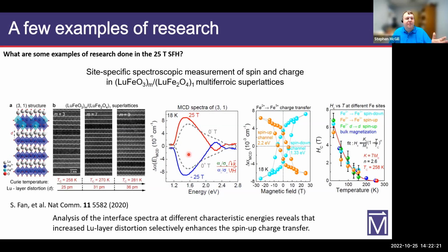So as we were talking about earlier, sometimes light is used to control or to tune the properties of the system. Well, here's an example of a ferroelectric ferromagnetic system. It's a superlattice of lutetium iron oxide. And it's a superlattice with different valencies of the iron oxide and different numbers of layers of those valencies stacked in between. And it turns out that these different ones have different Curie temperatures. So the goal here is, can we engineer a system that is both ferroelectric and ferromagnetic at room temperature? And because there's such a large change in the Curie temperature, we'd like to know what's going on in the magnetic system. Well, with light, we can do that.